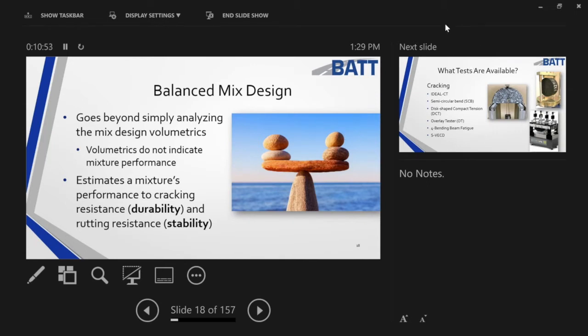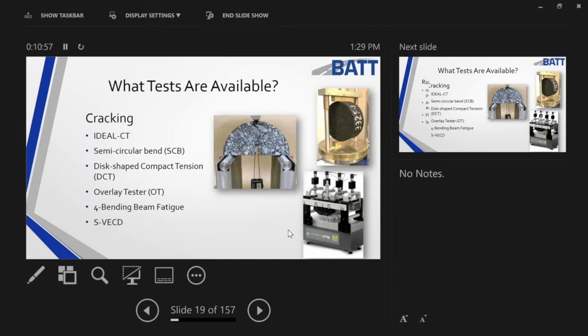Okay, so what tests are available? We've got everything from the high-end stuff to more of the simplistic. Now, I say simplistic, but they're not all that simple; some are more simple than others. If I'm going to look at cracking, and I'm using a very generic term for cracking, because I know we have thermal cracking, we have thermal fatigue that can introduce block cracking, we have the higher strain fatigue for reflective cracking, and we have lower strain fatigue that we look at for bottom-up cracks.